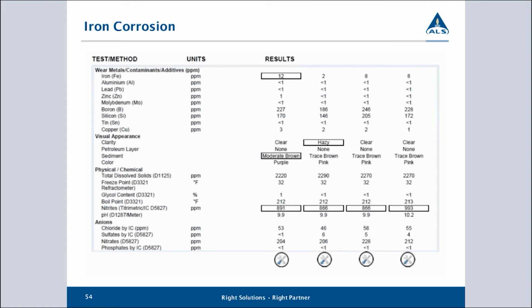And here we have an example where we're seeing corrosion starting to happen. We can see that iron has now risen to 12 ppm in the sample, and this would suggest that we're starting to see the start of active corrosion in the system. What's also concerning is we're seeing a moderate deposit of brown particles. These are almost certainly iron flakes, basically rust that's been carried around in the coolant. The most likely scenario is that our inhibitor level is too low. This looks like a conventional coolant. It's not a hybrid coolant. It's just a straight conventional coolant.